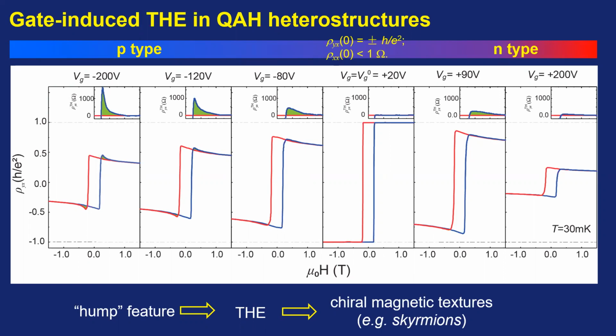Is there an explanation why the other usual suspects of elements that might give you magnetism do not? Actually, in my PhD, I was trying all the transition metals first in the periodic table, and I found just 3 elements can get this kind of ferromagnetic property. One is chromium, the other vanadium, and the third one is manganese. The reason I chose chromium first is because theory said chromium is better. The theory also said iron-doped TI is a best choice, but in our experiment we found there is no hysteresis loop in iron-doped TI. So that's the reason we built up the vanadium-doped system, because as I mentioned, the ferromagnetic property is better. I'm an experimentalist. I see this ferromagnetic property is good, so I want to try it.